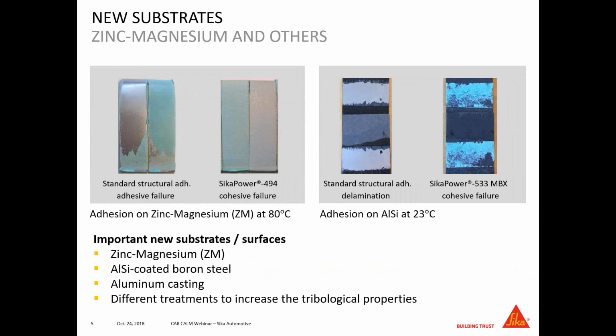However, this coating can lead to adhesive failure at elevated temperatures, and for this specific material, we had to develop a new material in order to make adhesion work again and see cohesive failure in these test specimens. On the right side, you can see an aluminum silicon coated boron steel. This coating has a somewhat weak connection to the steel, and therefore with a very strong structural adhesive, you can delaminate that coating. You need a more flexibilized system, as shown on the right side of the picture, with the Sika Power 533 MBX material, which greatly reduces the peak load that exists in this test, and therefore the material breaks cohesively rather than peeling off the coating.